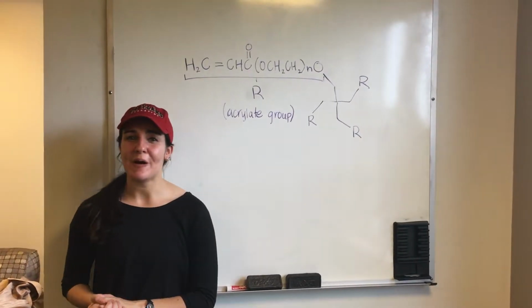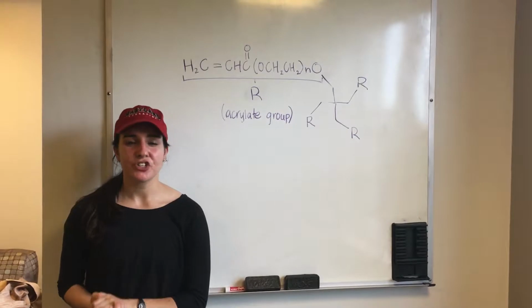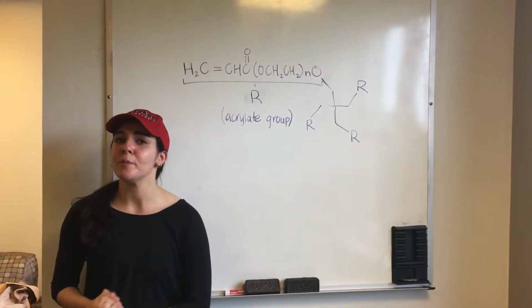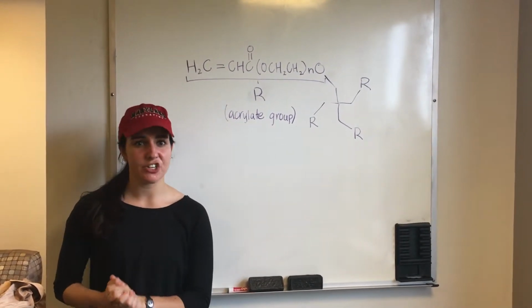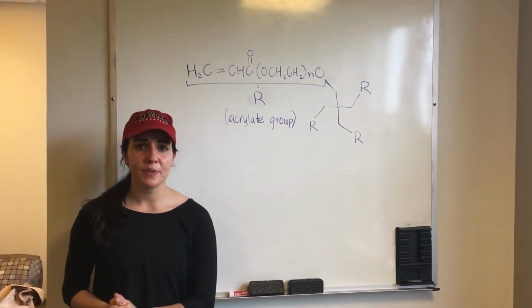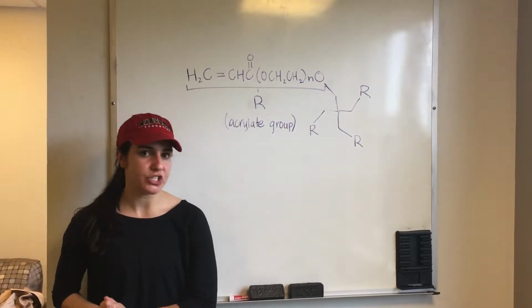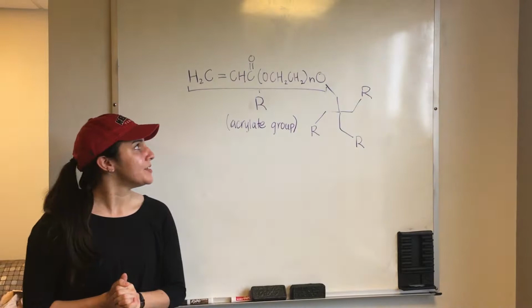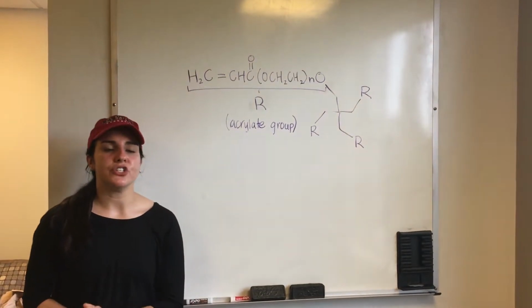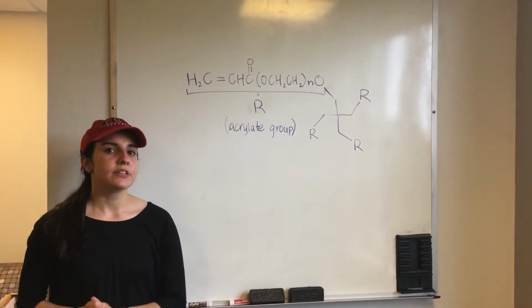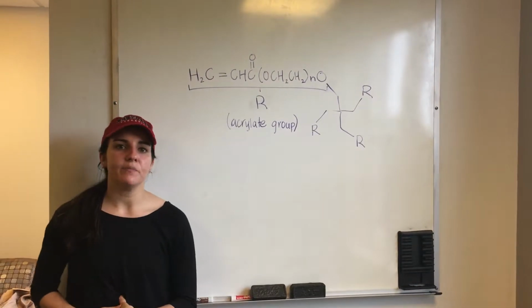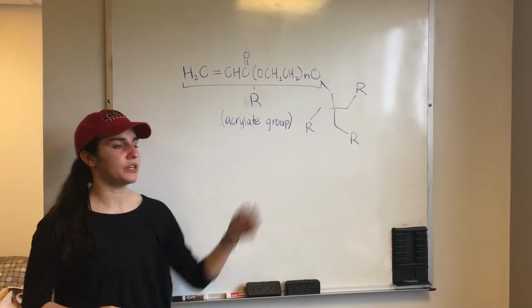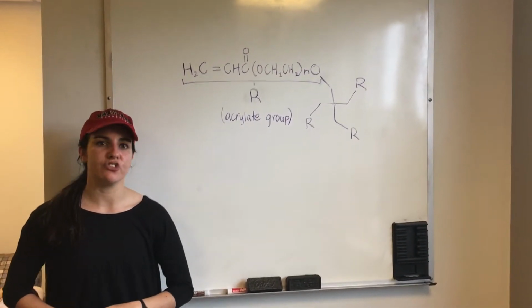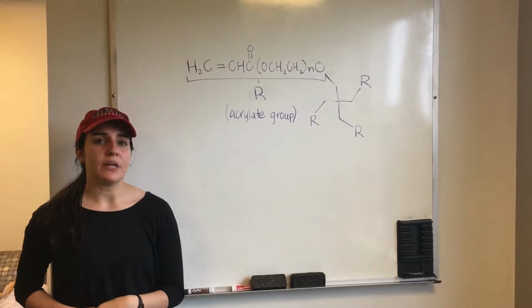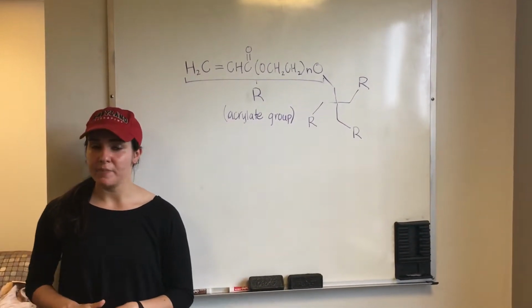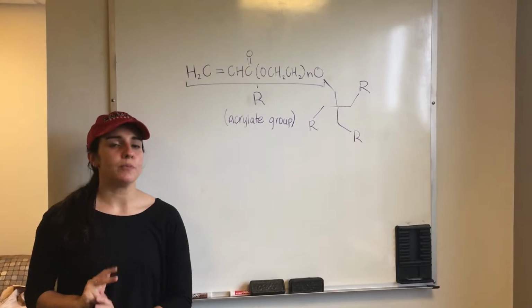Now I'm going to talk about our polymer selection. We initially considered several different biocompatible polymers such as PCL, PHEMA, and PGS. Ultimately, we settled on PEG, polyethylene glycol, a material that has been previously used in the tissue engineering and biomaterials lab. We selected a 4-arm PEG acrylate because we thought that the 4 functional groups would contribute to network formation in our hydrogel. We also selected PEG because of its affordability, high biocompatibility, and considerable mechanical properties.